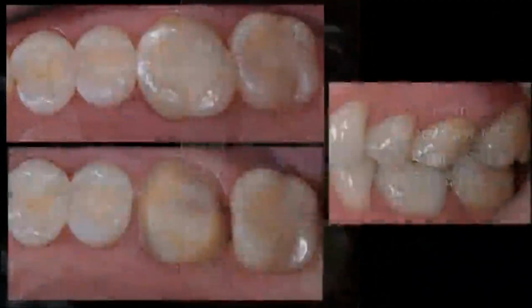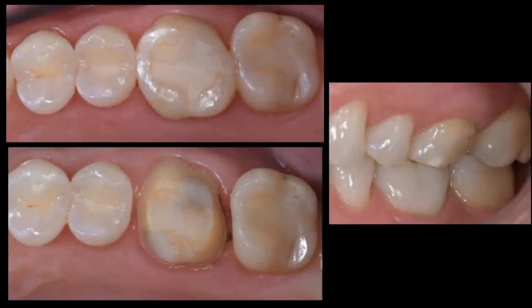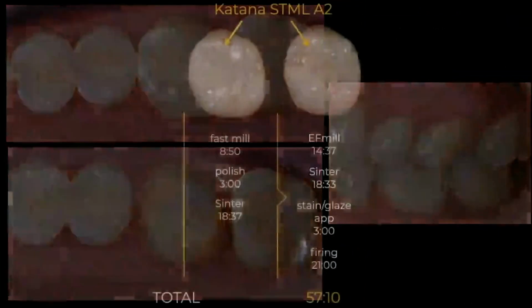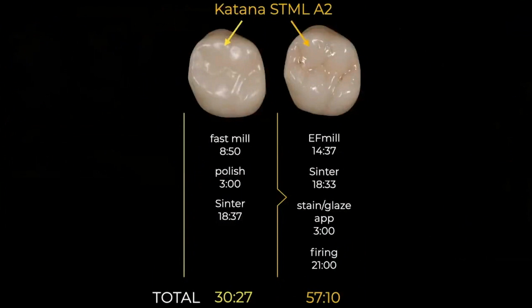And here's another case. So this was a case that was prepared for a crown on the tooth number 14, the upper left molar. And for this case, I wanted to play with comparing and contrasting different milling time modes versus polish and stain and glaze. So here you'll see on the left, I milled that restoration out on fast mill. That was about almost 9 minutes. And then I just polished it and sintered it. So that whole time took me a little over 30 minutes.